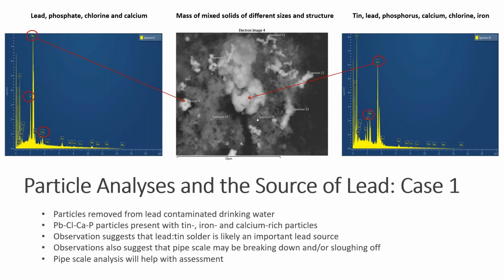But this is just an example focusing in on the particles themselves. These were just some samples that we collected from a community, and particles were removed from a water that really has had a long-term problem with lead release. What we see here is under the scanning electron microscope, and you see a mix of stuff. The shading really reflects the weight of the solids. So lighter colors represent heavier, like lead elements, whereas the darker represent lighter elements.